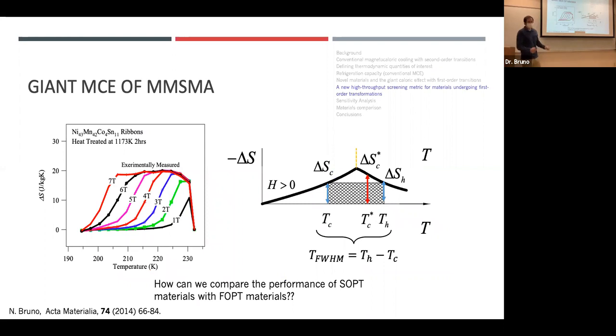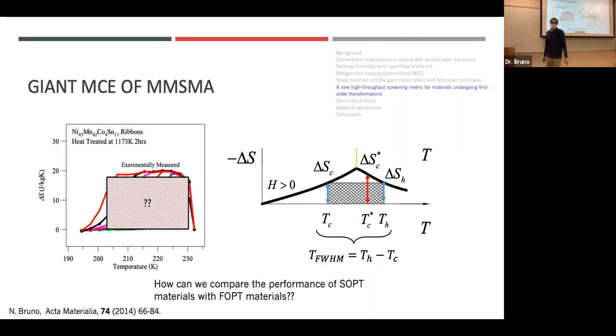Okay, so I want to develop a performance metric to compare all these different metamagnetic shape memory alloys, and I want it to be consistent with the reversibility in non-SMAs. So how do we do that? This is what our delta S versus temperature looks like for a shape memory alloy around its first order transition. This is what a delta S versus T diagram looks like for a ferromagnetic material. What do we do? We just integrate it like they did, like make a box or something, and integrate? I don't think so. We can't do that because it has different reversibility. This material has thermal hysteresis, has losses. This stuff does not.